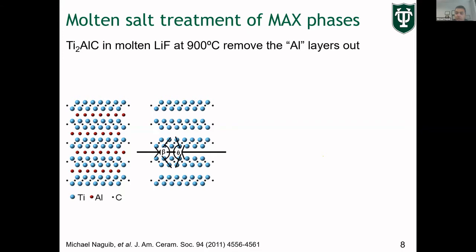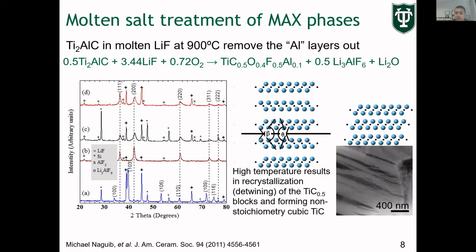But due to the high temperature, what happened is detwinning of the titanium carbide blocks, and we formed a rock salt structure of titanium carbide, cubic titanium carbide. So it was not electrochemically active at that time, and was not that interesting for the application we were trying to do.